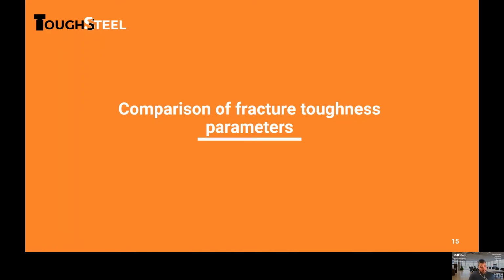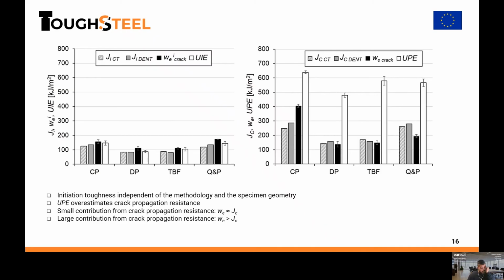However, let's see what happens when we compare the different fracture parameters obtained from the different methodologies, which is interesting to understand a little bit more what the meaning of the different fracture parameters is and what the most appropriate is, when we want to measure the crack initiation or the crack propagation or the overall fracture performance. Here we did this exercise to compare these different fracture toughness parameters. On the left here, you can see the parameters related to the initiation: this JI value, remember, described at the beginning, this essential work of fracture at crack initiation, and this unit initiation energy.